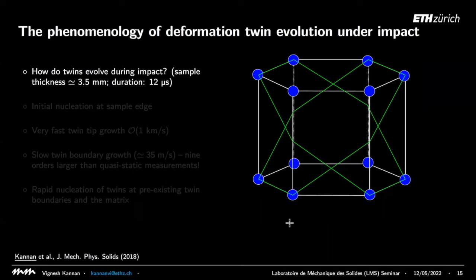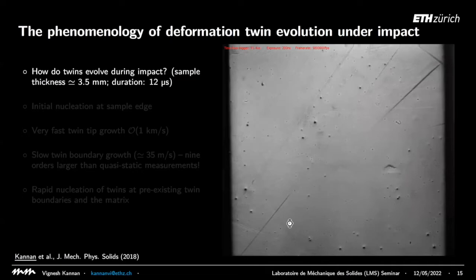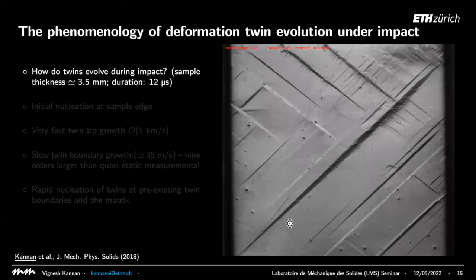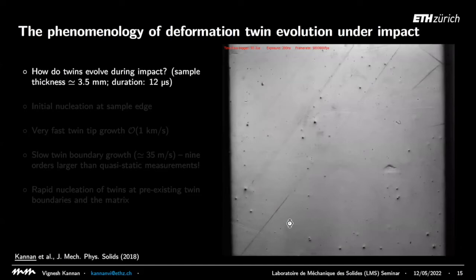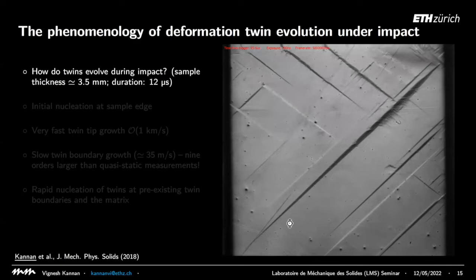For the experiment, we took a single crystal of magnesium. These marked planes are the planes along which twins propagate, but we image the outer plane surface — a projection of the deformation propagating on these three-dimensional surfaces. What you see in the high-strain-rate impact experiment movie: the total duration was 12 microseconds and the sample width was about 3.5 millimeters. The compression is along the horizontal direction; these heterogeneities are the deformation twins that propagated during the 12 microseconds of real-time loading.